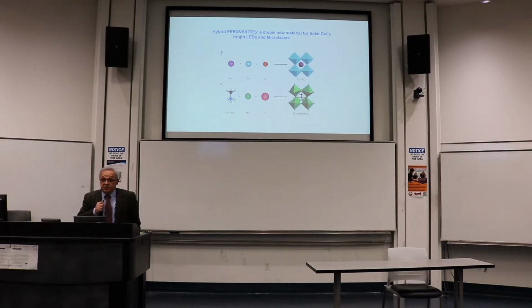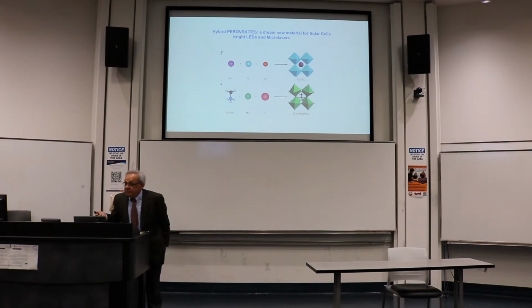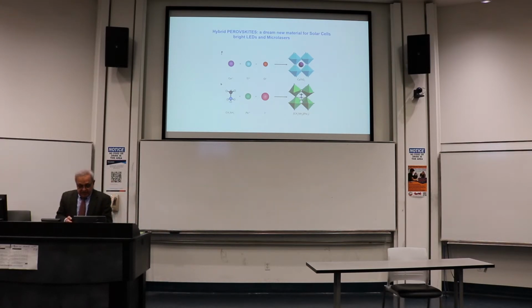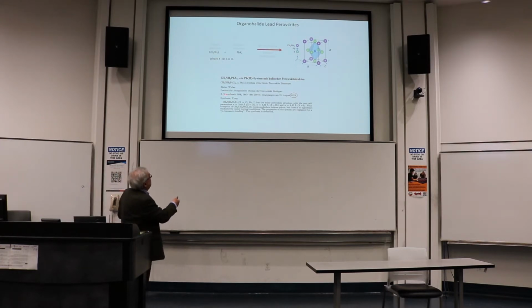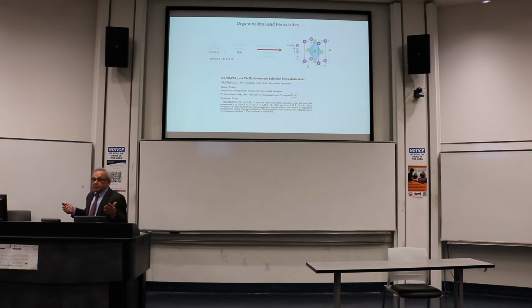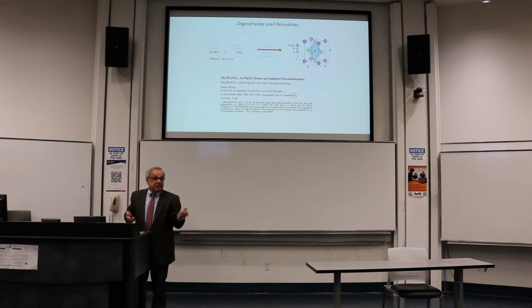So the material about which I'm speaking today is quite different, because the cage is filled with an organic molecule, not with titanium or calcium. It is filled with methylamine, CH3NH3. And it is a dipole, an electrical dipole. It has a minus end and a plus end. There is enough space here. So this type of molecule was found by serendipity by another German, Dieter Weber. He described CH3NH3PbX3 in '78, a long time ago, but nobody paid attention. It was sitting somewhere in the lab. It can be created from solution like kitchen salt. Basically, this is the same ionic crystal as sodium chloride.